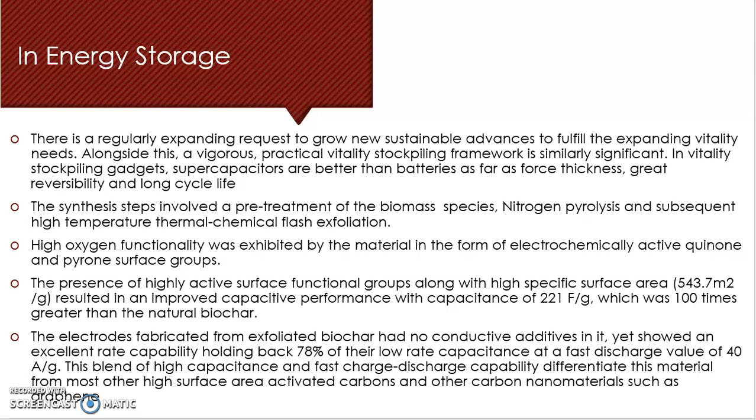Genovese et al. explored the electrochemical performance of biochar derived from corn cob, which is an agricultural residue, as supercapacitor electrode. The synthesis step involved a pre-treatment of the biomass species, which is nitrogen pyrolysis, and subsequent high temperature thermochemical flash exfoliation. High oxygen functionality was exhibited by the material in the form of electrochemically active quinone and pyrone surface groups.